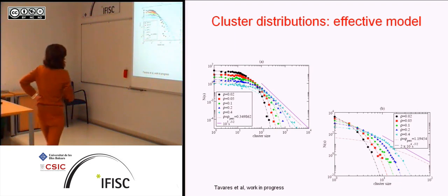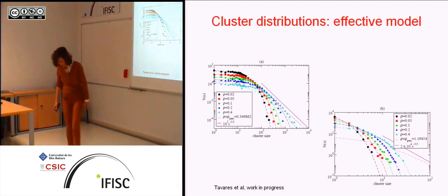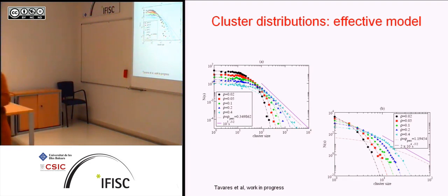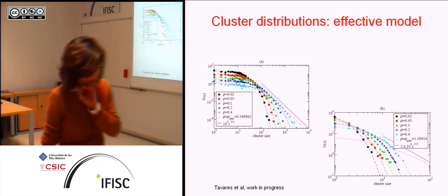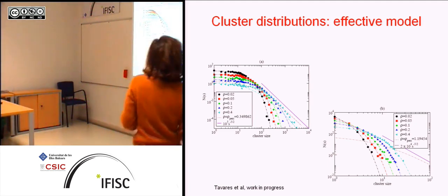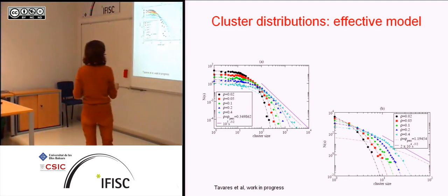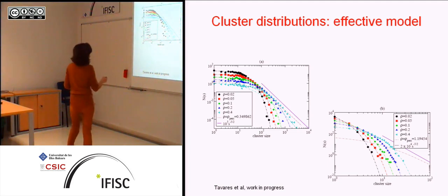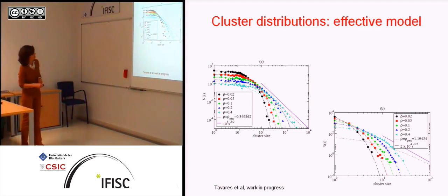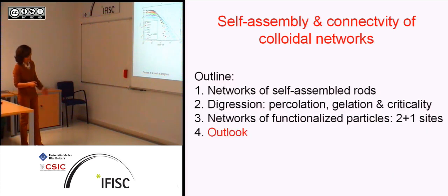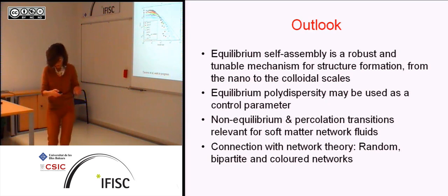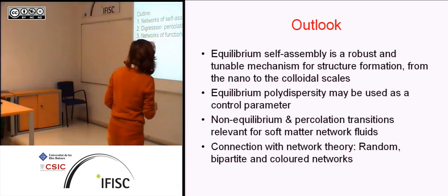But presumably, I think we don't have an integrated system. I want to finish with a completely different problem that I'm not going to bother you about, but one of the funny things we did was actually quite funny. We could not actually calculate the first distribution functions to this generalized model, but we invented an effective model which is marvelous. I mean, it's as good as the real thing compared with the simulations of the real model. And these are just cluster distribution functions, number of clusters of size S, independent of which bonds are in that cluster, just counting the number of particles. S is just number of particles, and the number of clusters of a given size. And at least in the non-percolated region, this effective model is quite wonderful. And this is more or less it.